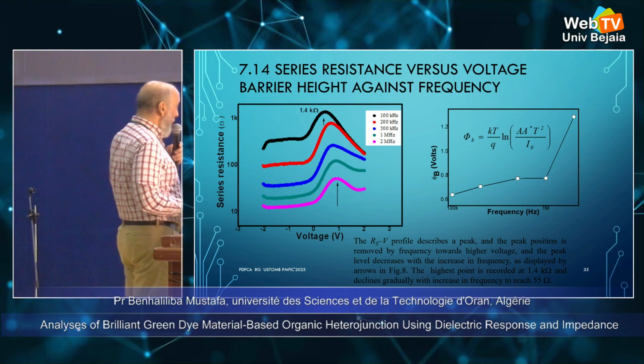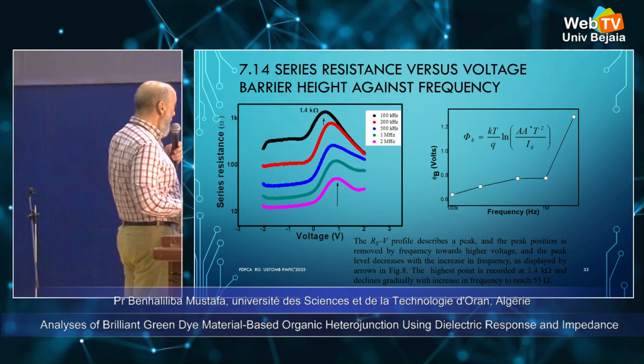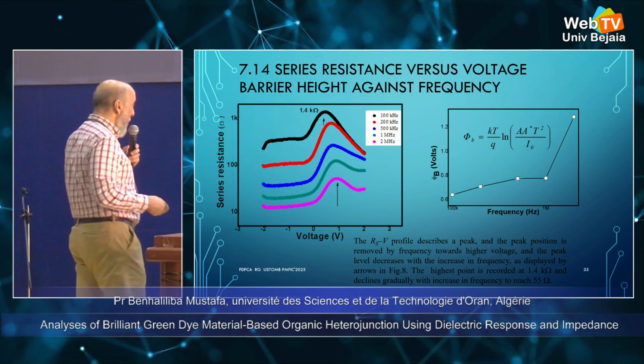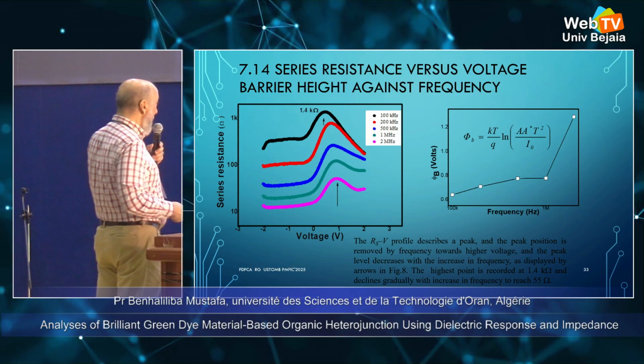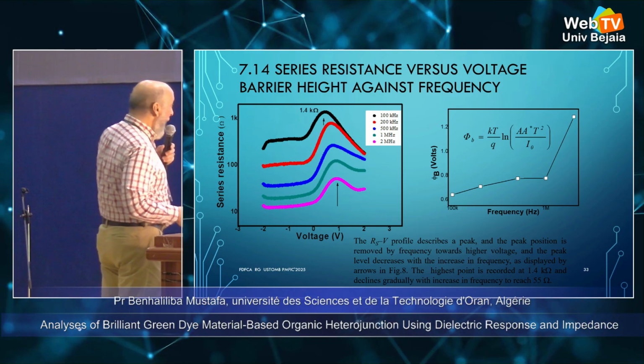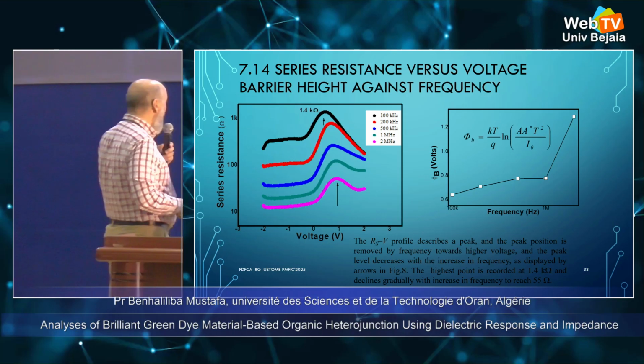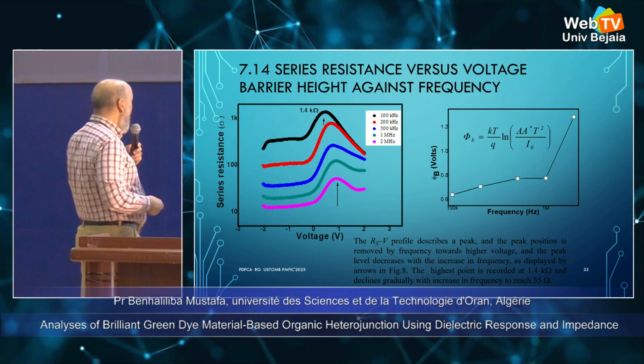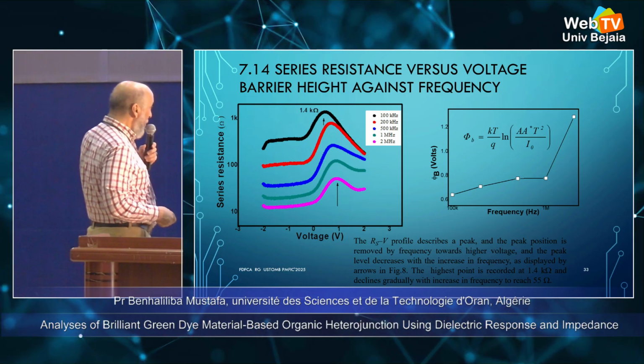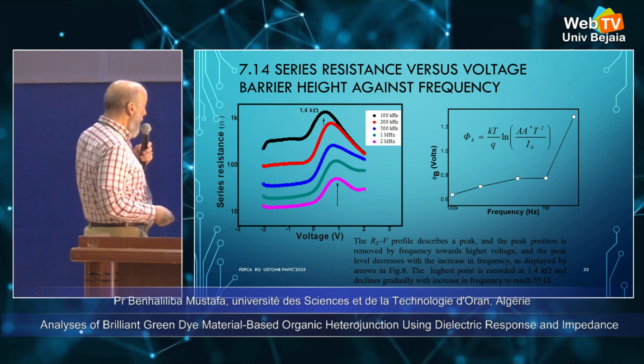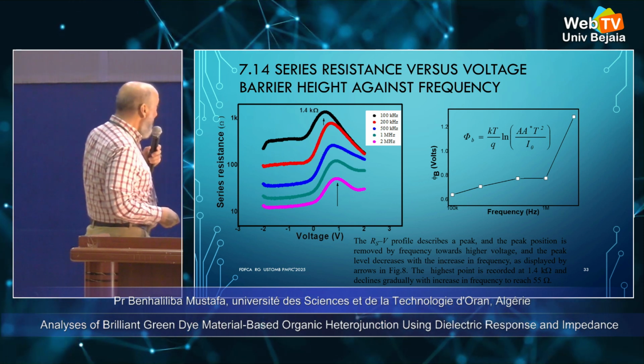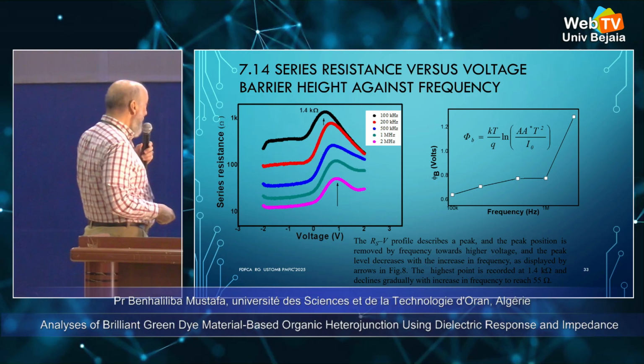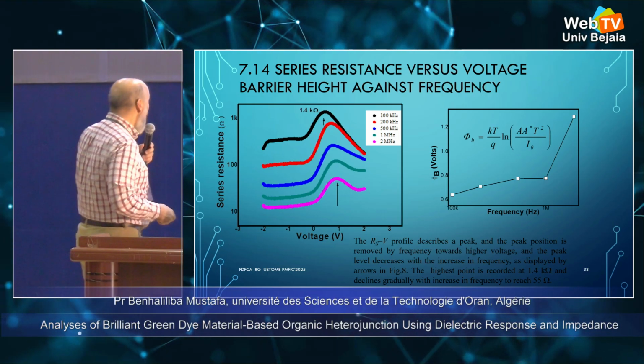The Rs-V profile describes a peak, and the peak position moves with frequency towards high voltage, and the peak level decreases with the increase in frequency, as displayed by the arrow in figure 8. The highest point is recorded at 1.4 kilo ohm and declines gradually with increase in frequency to reach this value.